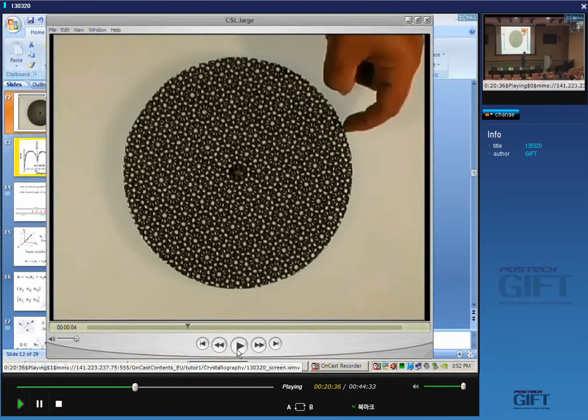And let's assume that we have 1/3 of the lattice points in exact coincidence. Then we say that that boundary is a sigma 3 coincidence site lattice boundary. Okay? If 1/5 of the lattice points are exactly coincident between the two, then we say that it's a sigma 5 boundary. So a sigma 5 boundary will have a somewhat higher energy than a sigma 3 boundary because only 1 in 5 of the lattice points are coincident. Okay? So everyone happy with that concept?